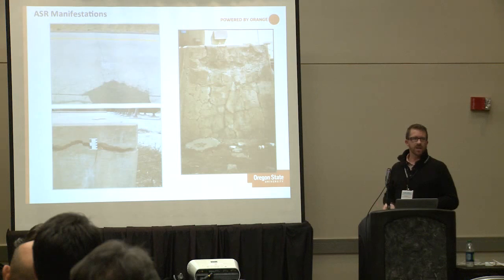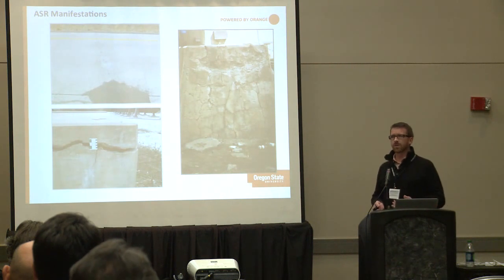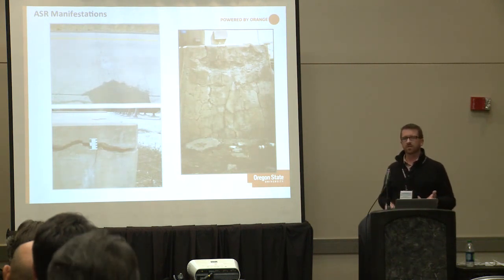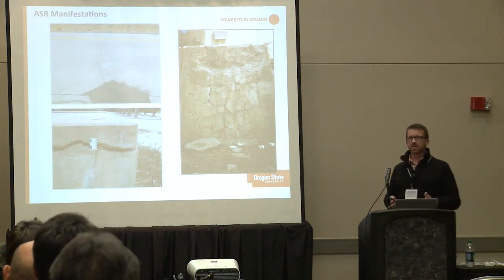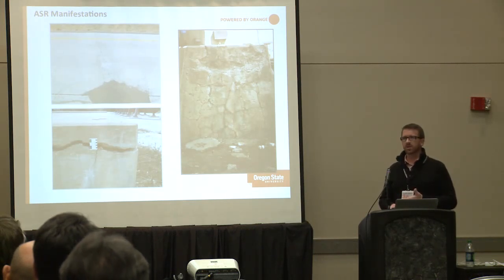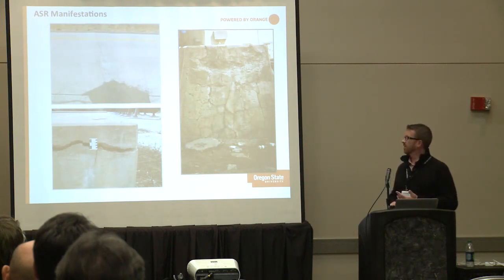This structure was taken out of service over the past year due to ASR, but also due to corrosion and freeze-thaw attack. A lot of times ASR doesn't necessarily lead to the eventual loss of integrity of a structure, but because it starts cracking it opens up a fast path for other forms of attack — chloride ingress, carbonation, corrosion of reinforcing steel, freeze-thaw attack, and sulfate attack.